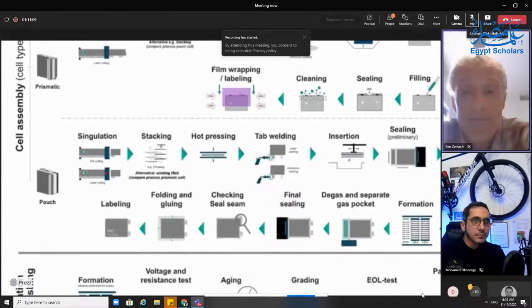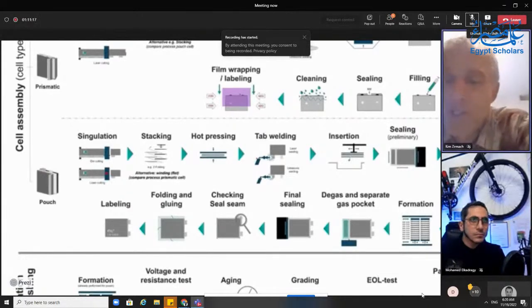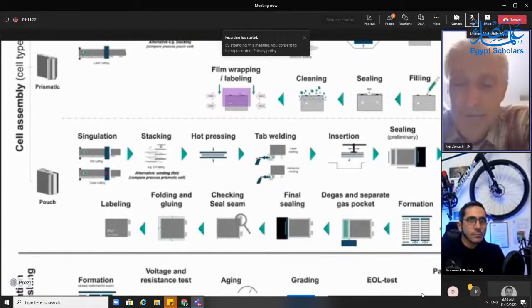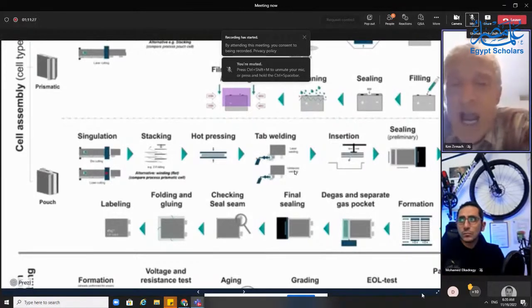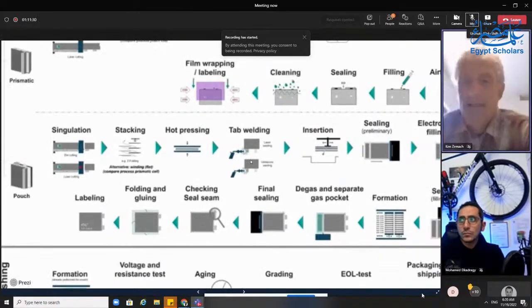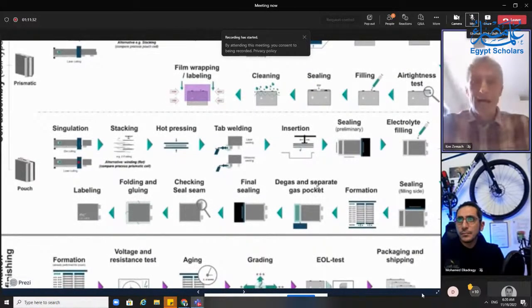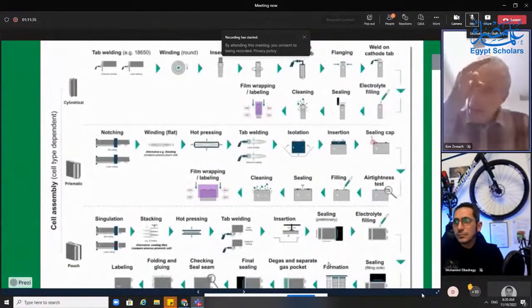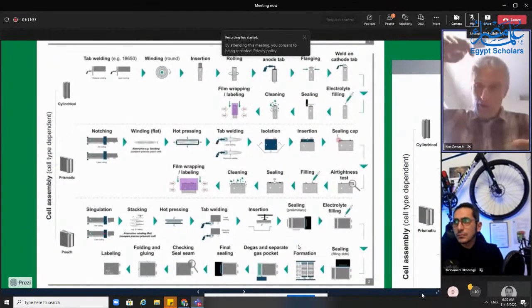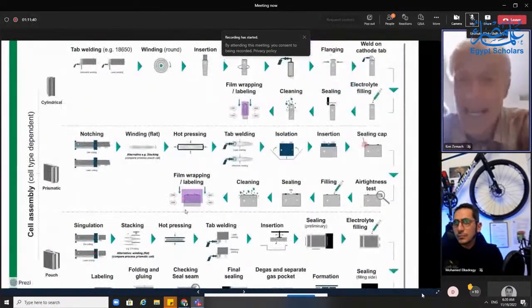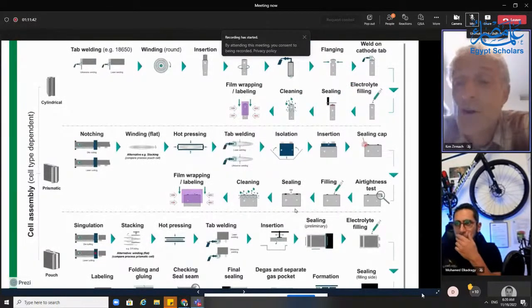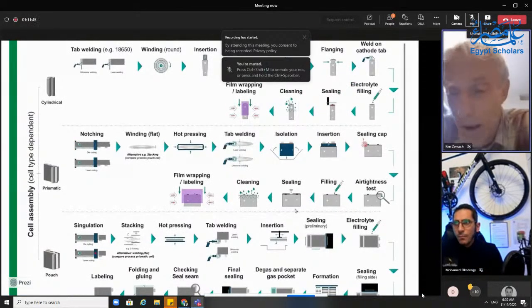You're not completely sealing it, because now we've caught up with the cylindrical. Now you need to get that electrolyte in. So you've got to fill your electrolyte. On a small cylindrical cell, you put in however many grams, 4 grams, 7 grams, depending on the size of your cell. In a giant prismatic cell, like some of these big cells, you've got a tiny little fill hole. And so you put in all the electrolyte you can, and you can't get in enough because it hasn't soaked in, because there's a transport problem.